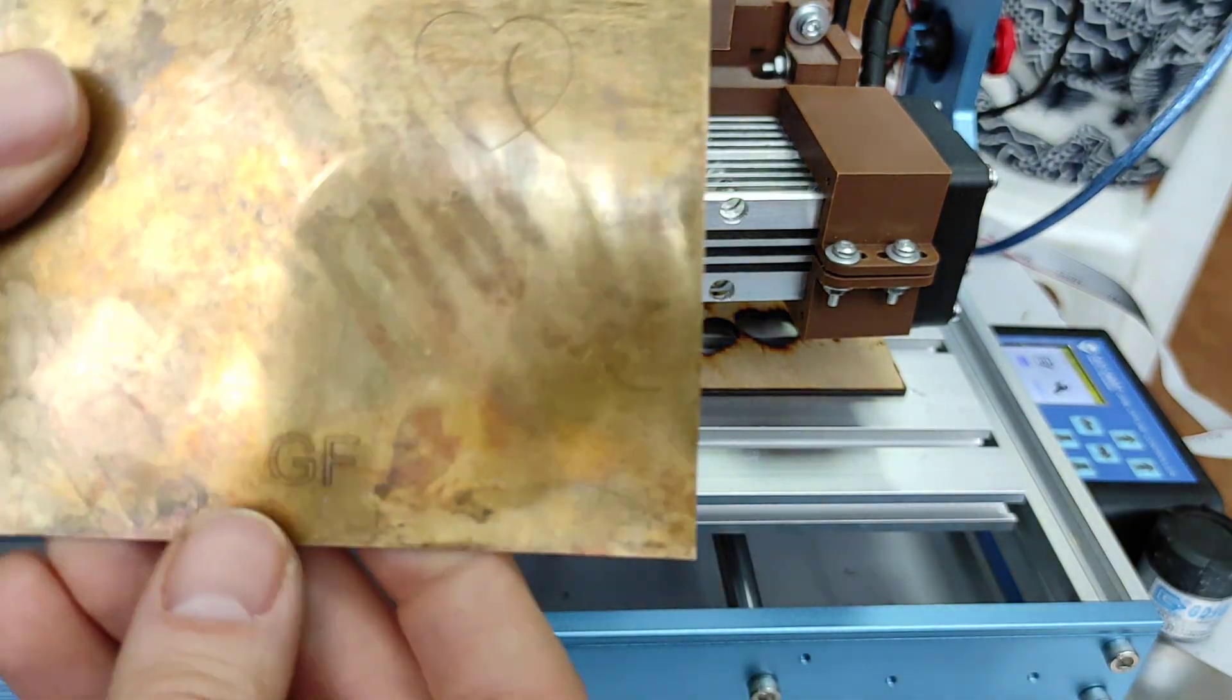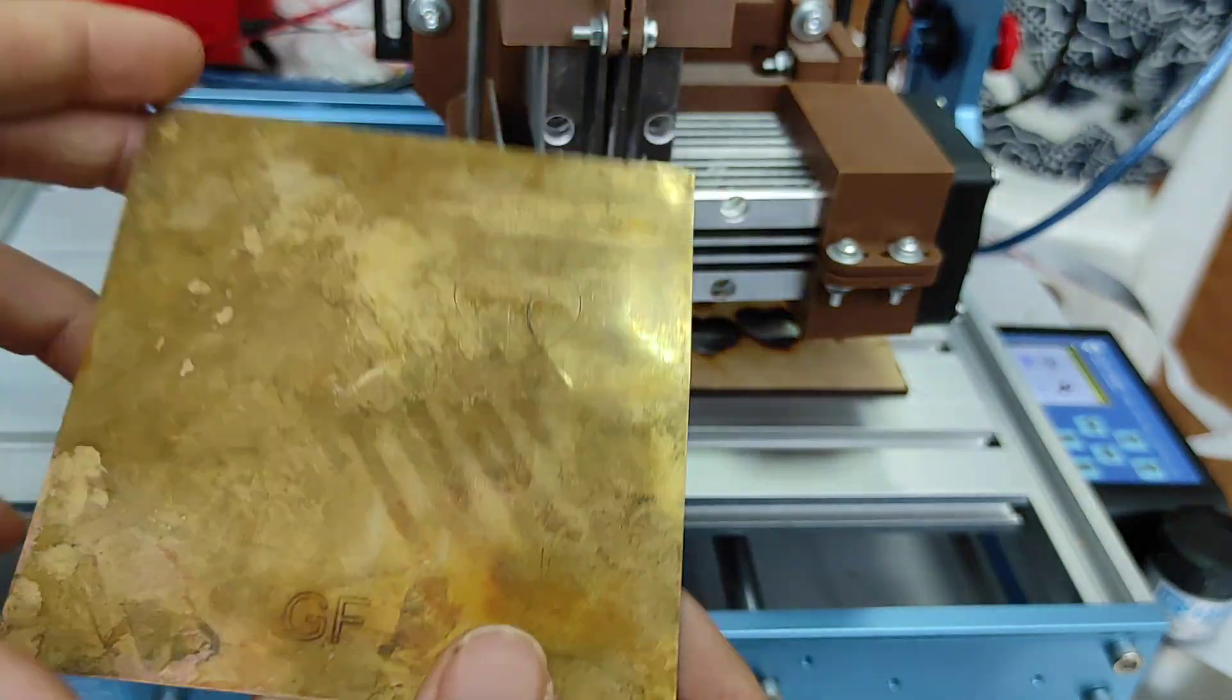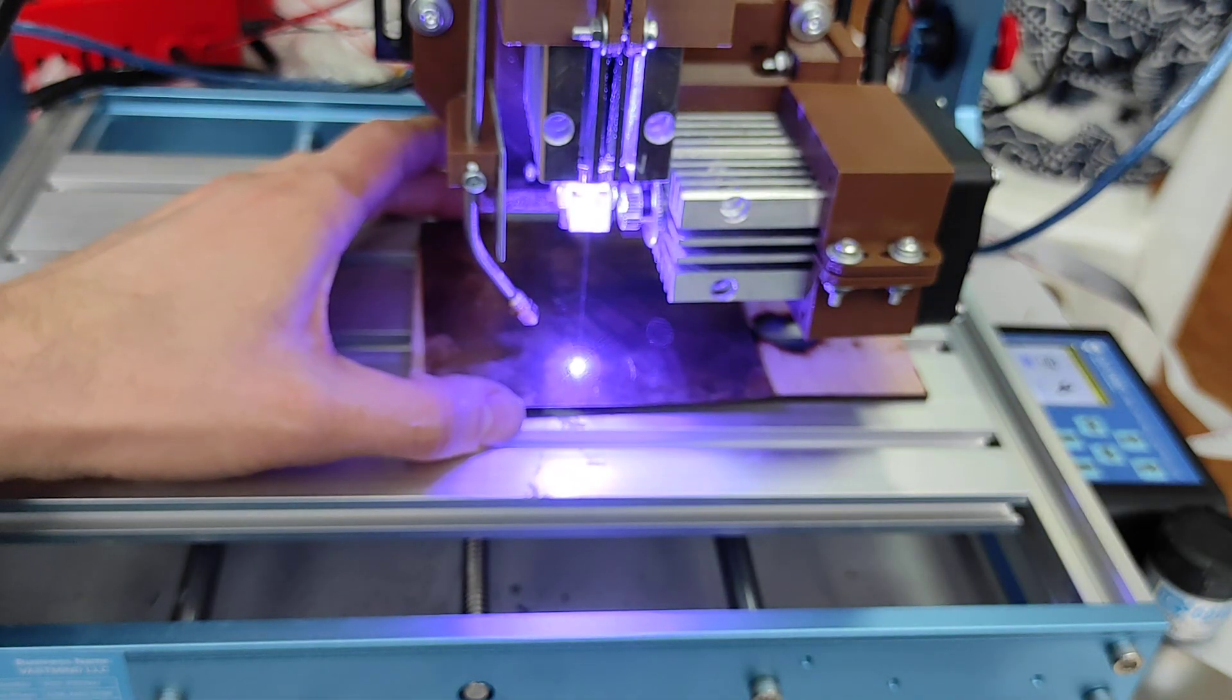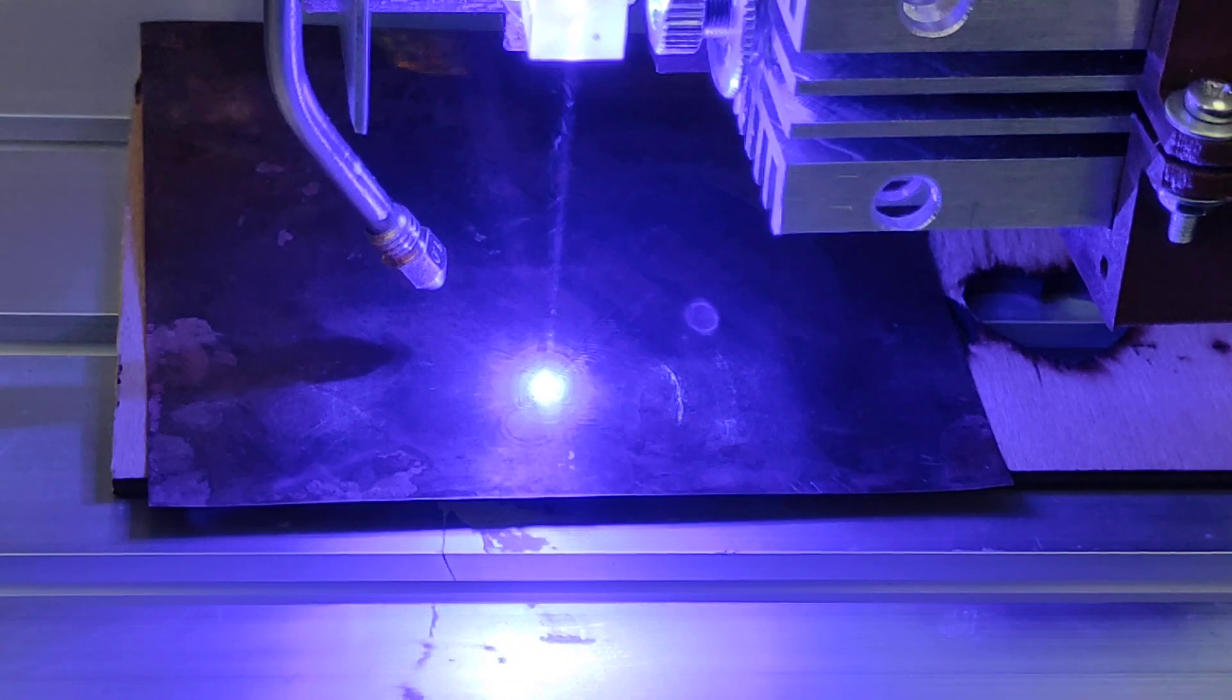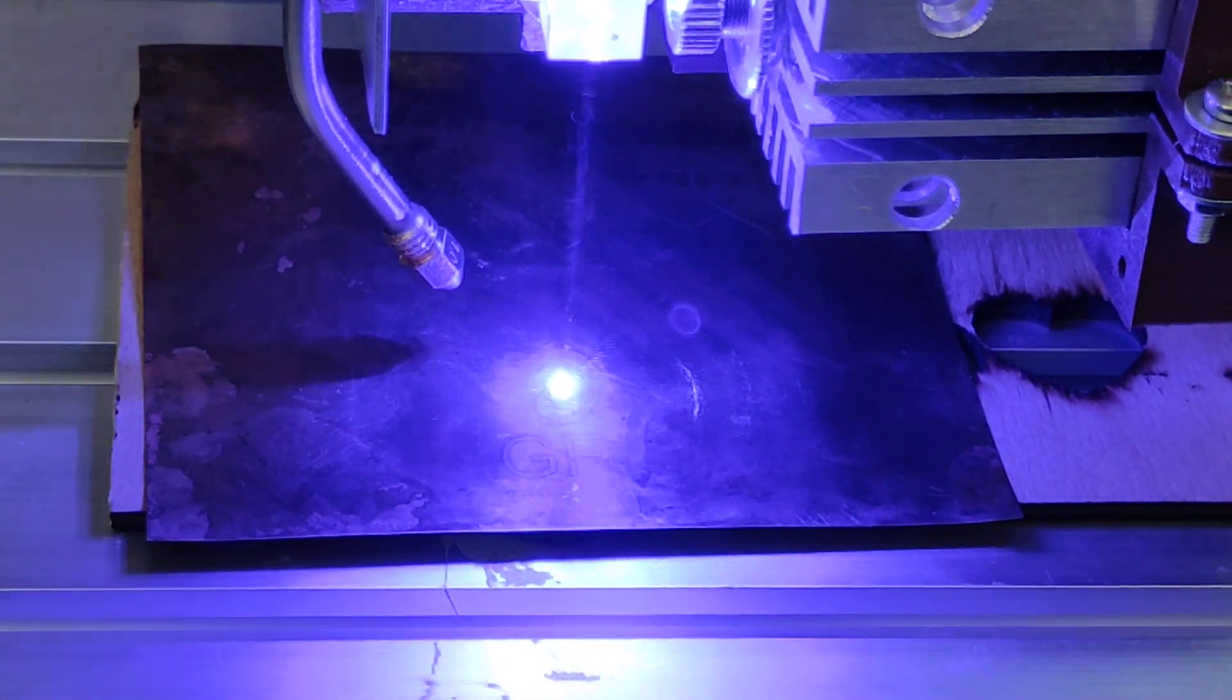The last thing I want to show you is that you can even engrave on pure brass. It's very thin, like one millimeter piece of brass that you can buy on eBay or Amazon. Let's check the focus first and our starting point. The speed is 100 millimeters per minute and 99 power. The hack is that you don't need any engraving paste or any chemicals, you just have enough power.